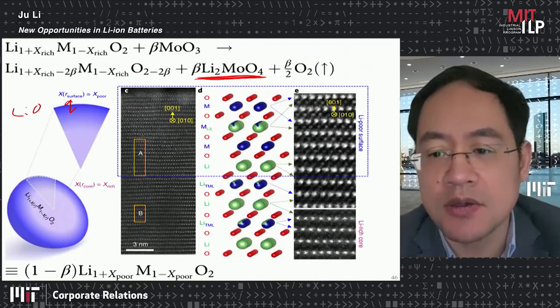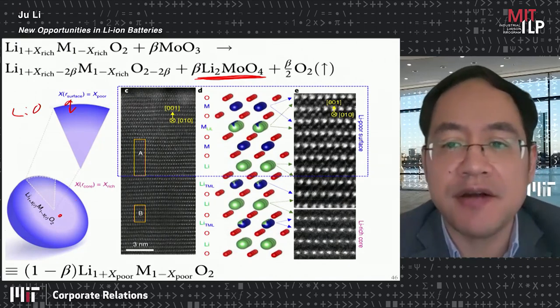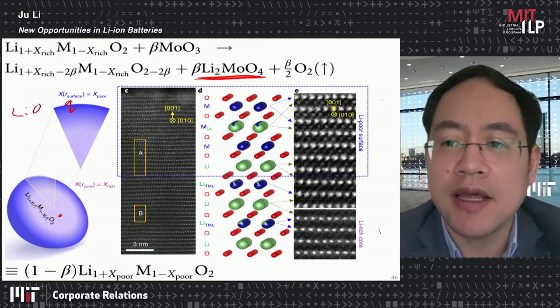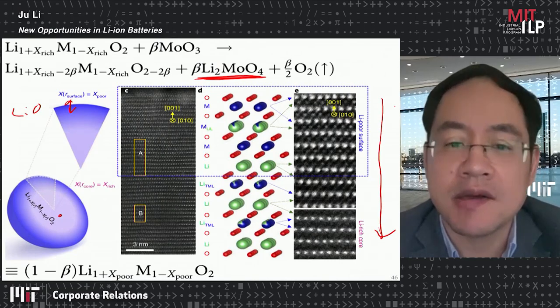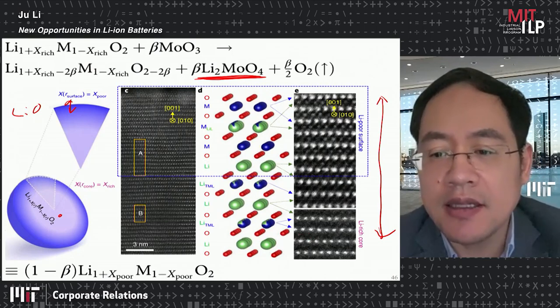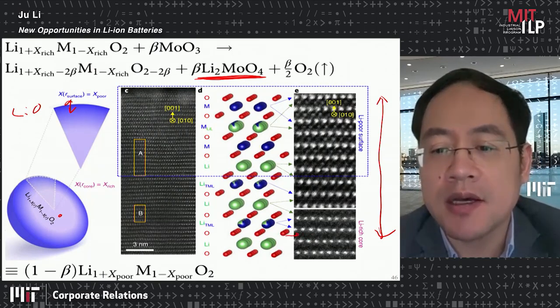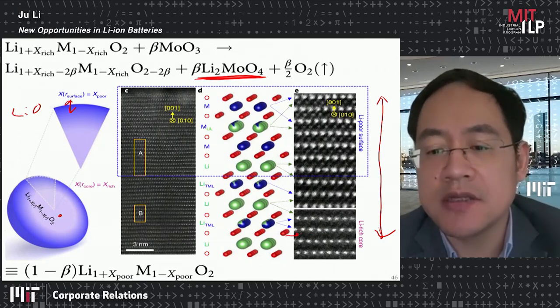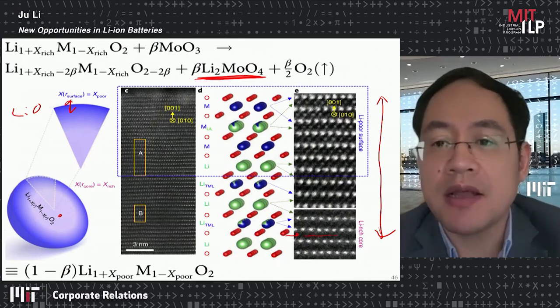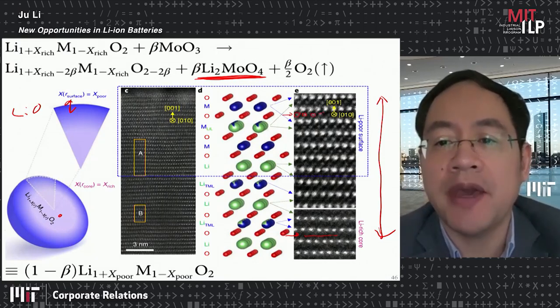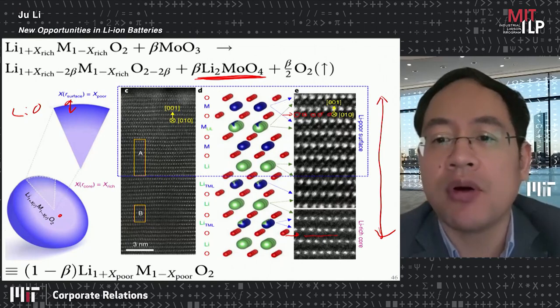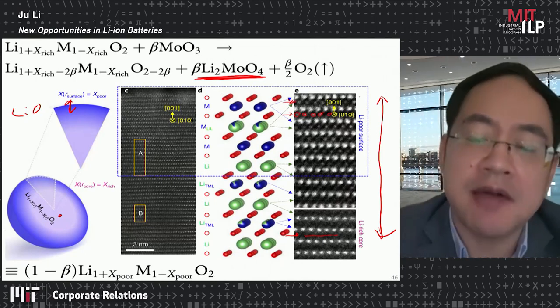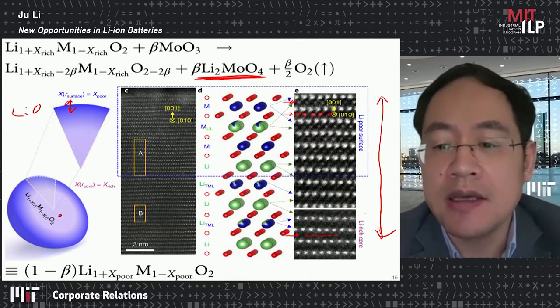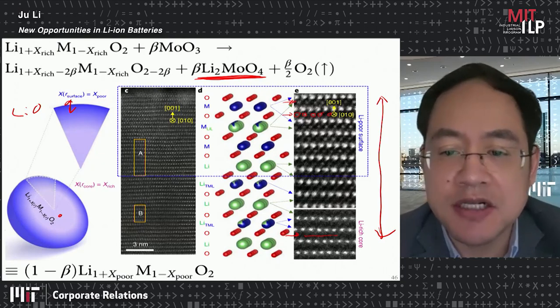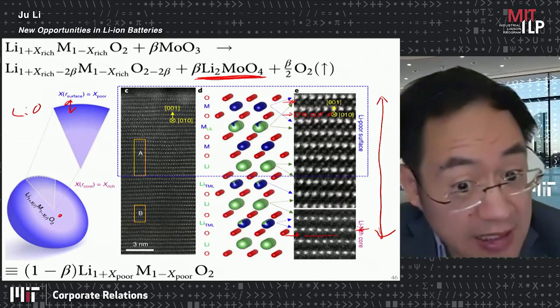And evidence is this. In the core, it's actually not very deep, this is just like 10 monolayers from the surface, just about 10 nanometers going into the surface. Here, in the lithium layer, you don't see anything because this is fully occupied by lithium. But as you go to the surface, you start to see these faint transition metal occupation. So that's proof that we have lithium-poor surface, because transition metals, which have TEM contrast, are occupying atoms in the lithium layer. Here we have lithium occupying the transition metal sites, but you cannot see them in the TEM.